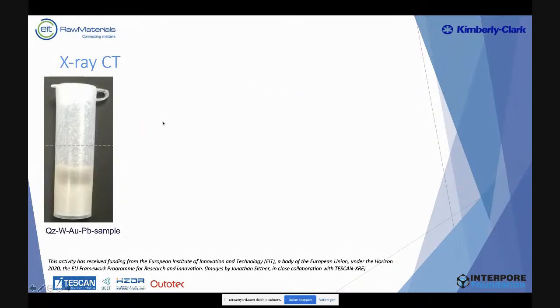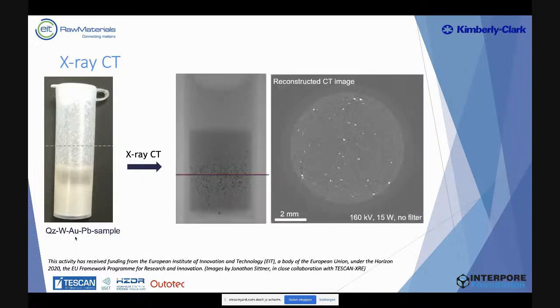This is the work of one of the PhD students, also in close collaboration with our partners in a European project. Here we have a mixture of grains where you have quartz, tungsten, gold, and lead. If you just do normal CT on the radiograph, you can already distinguish some highly attenuating grains. But if you reconstruct, you see bright spots, and those can be lead or gold. But without extra knowledge, it's impossible to say what we are talking about.